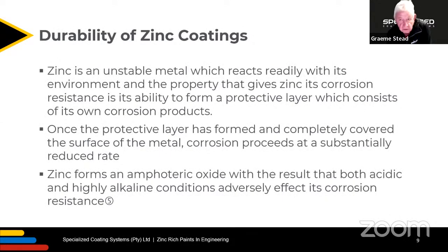Zinc is an unstable metal which reacts readily with its environment, and the property that gives zinc its corrosion resistance is its ability to form a protective layer which consists of its own corrosion products. Once the protective layer has formed and completely covered the surface of the metal, corrosion proceeds at a substantially reduced rate. Zinc forms an amphoteric oxide with the result that both acidic and highly alkaline conditions adversely affect its corrosion resistance. So Simon has very eloquently elaborated on that.